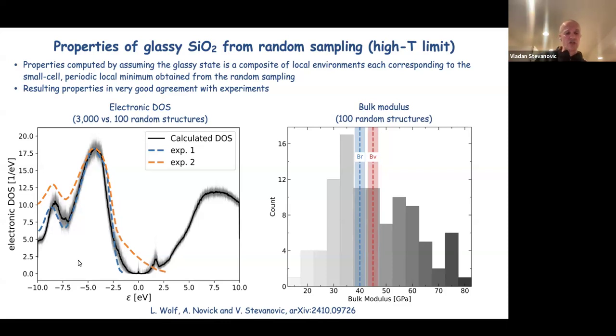One could, in principle, just pick 100 structures and get a lower accuracy result, but still very reasonably within experimental measurements. And in order to prove that 100 structures may actually be enough to calculate other properties, we calculated the bulk modulus now using 100 structures total.